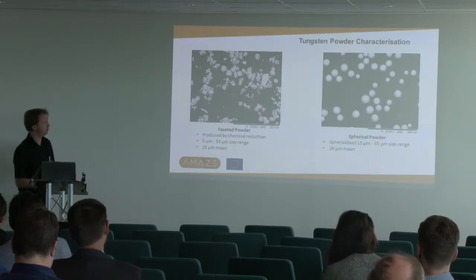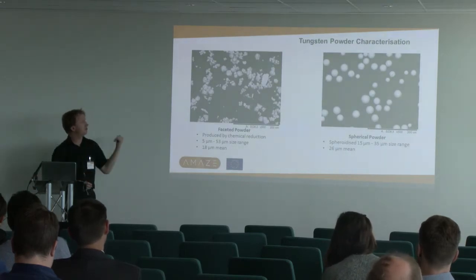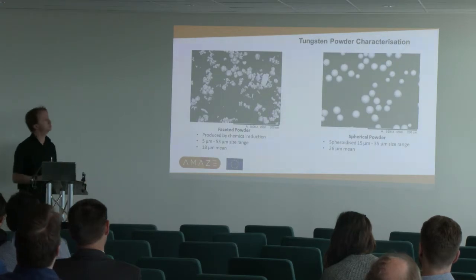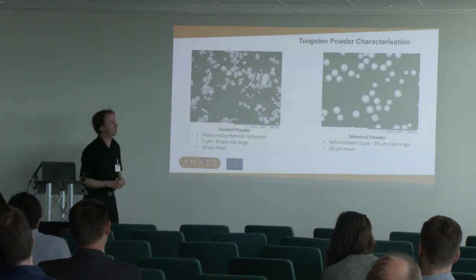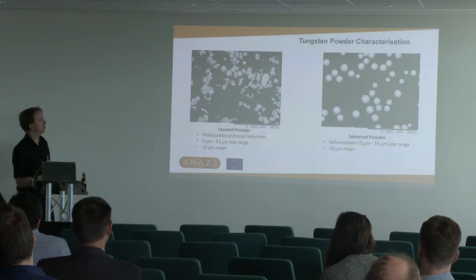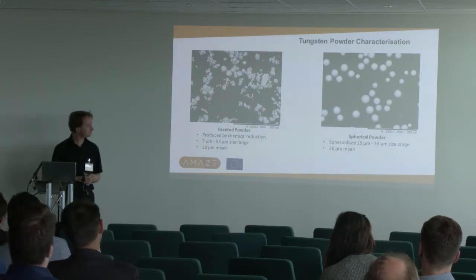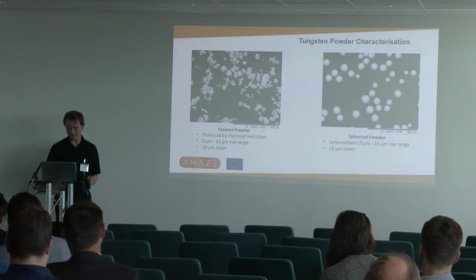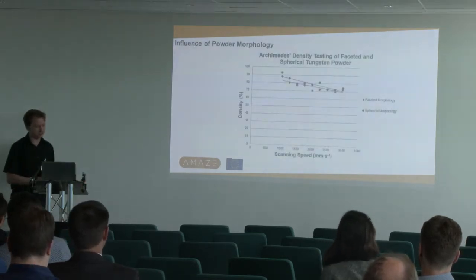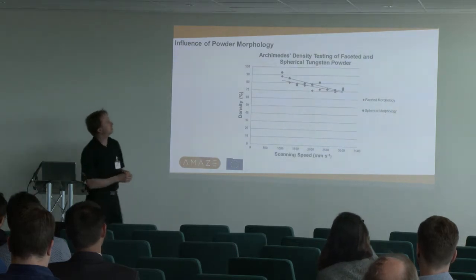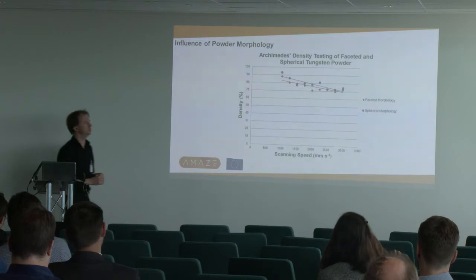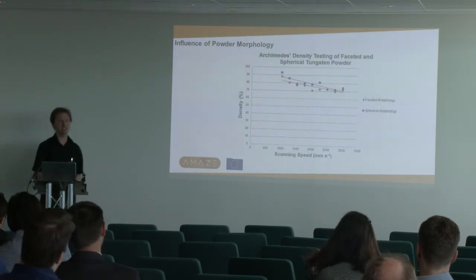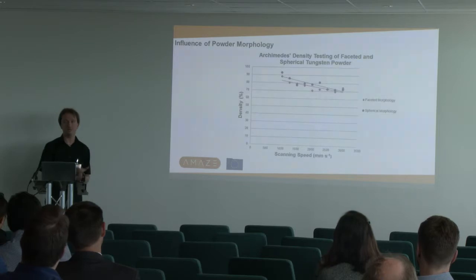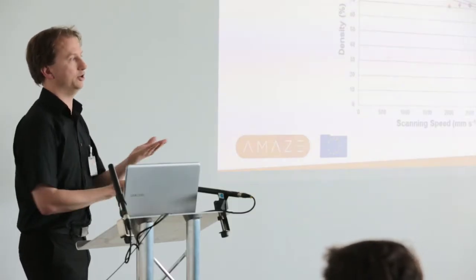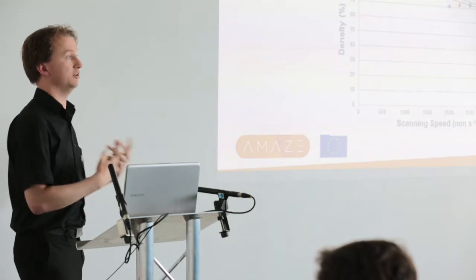So once again, we had two different powders. The powder on the left is formed by some kind of chemical reduction method. It's faceted and not really what you want to be putting in your powder bed machine. And then we've got a spheroidized powder on the right. It is always nice to compare these back to back. As you'd imagine, a similar sort of study here. You can see the blue line there is our nice spherical powder, which in terms of density is always outperforming that faceted powder. We believe that, purely from packing in the powder bed, we're getting too much argon trapped between the powder particles that's eventually converted into porosity, unable to escape during the melting process.